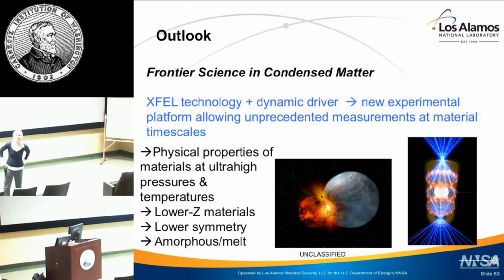Yes, sir. I have two technical questions. Yes, please. What's the time resolution on your X-ray emission measurements? Is it the duration of the probe beam? Yes, so actually the emission process itself is much faster. It's of the order, say, I want to say 120 femtoseconds. It's very short. Our probe is something like 60 femtoseconds. So we're still shorter than the emission lifetime. So again, I would categorize it as more of a snapshot, except it's coming from a volume of material that is perhaps multi-phase, right? So we have to be careful.